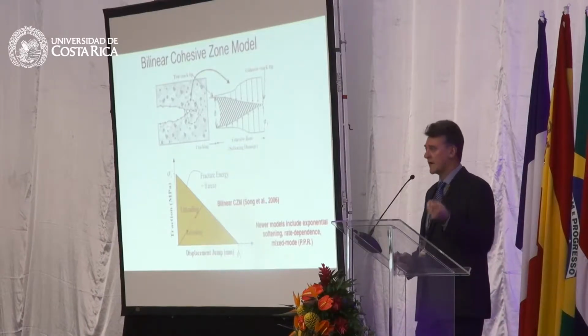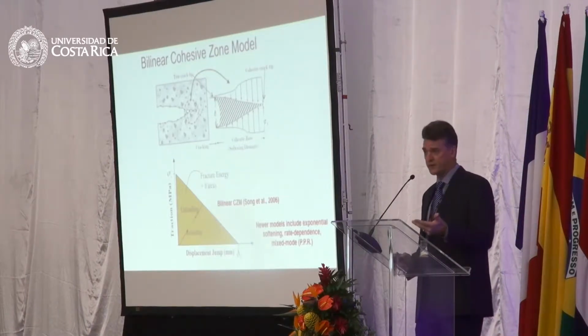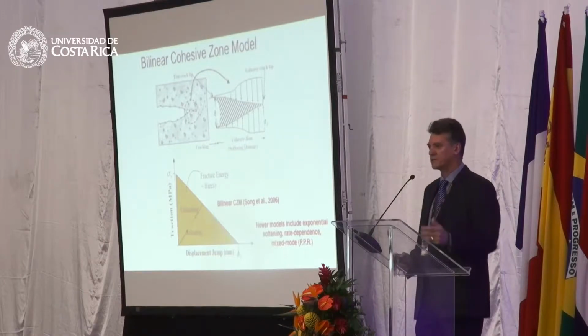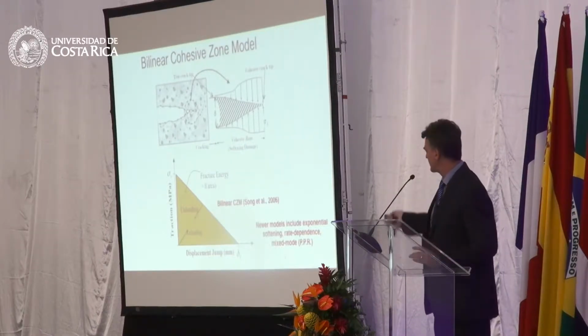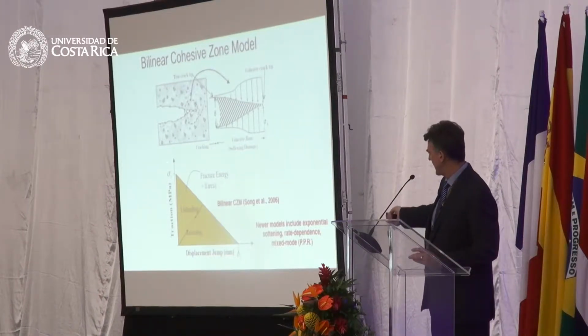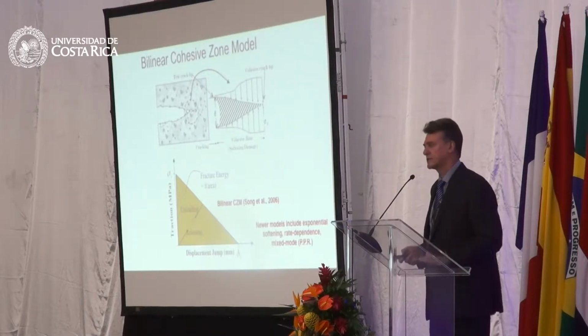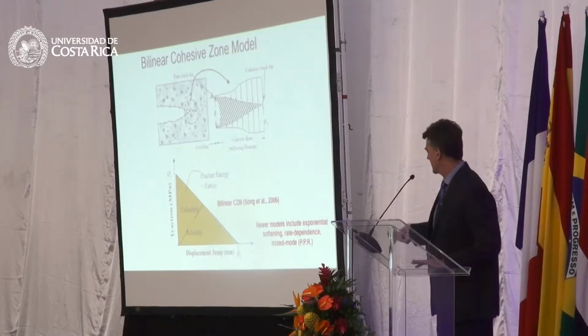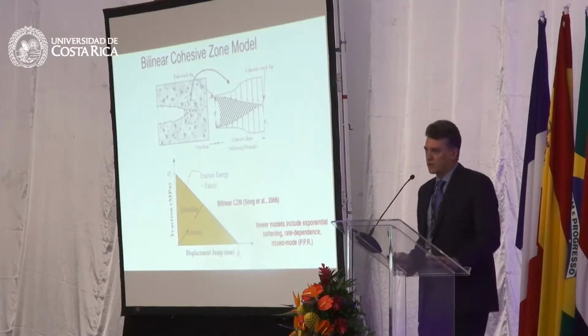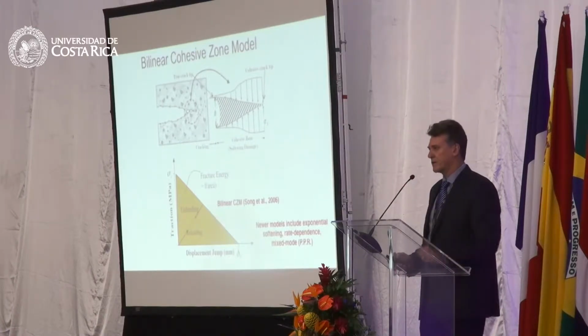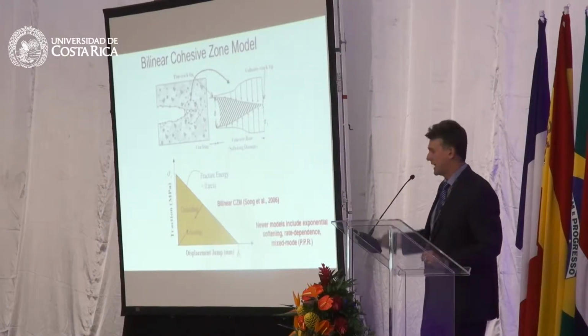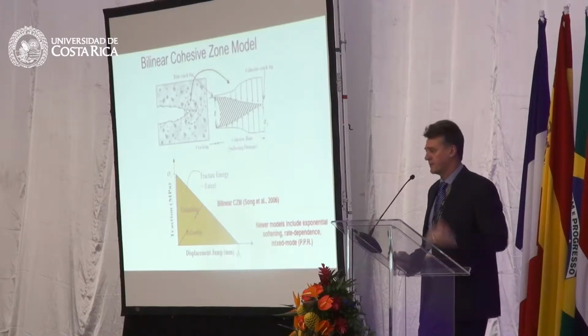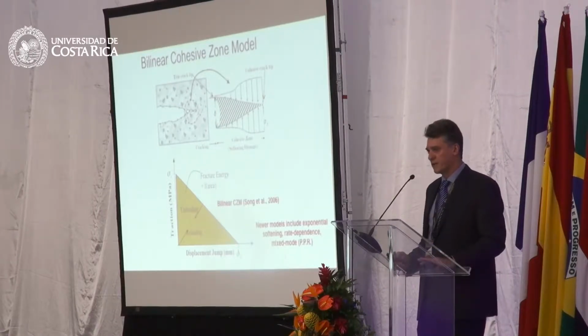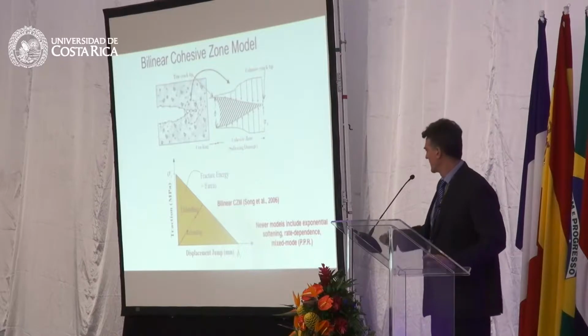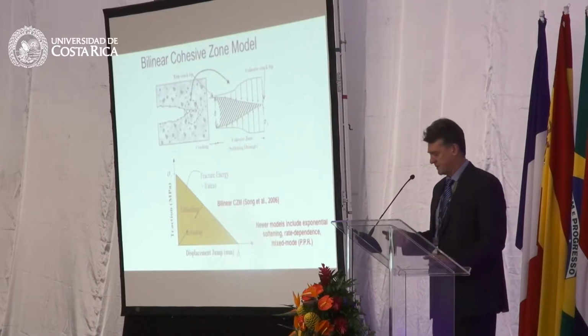It really is a crack resistant material, at least at first, until it starts to age or get moisture damaged. You can see that because there's so much energy consumed after the peak local stress in the material is reached. So any model looking at coalesced propagating cracks really needs to take into account this energy that happens post-peak.